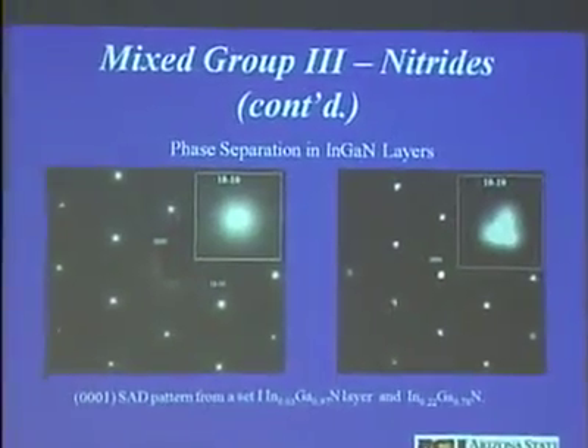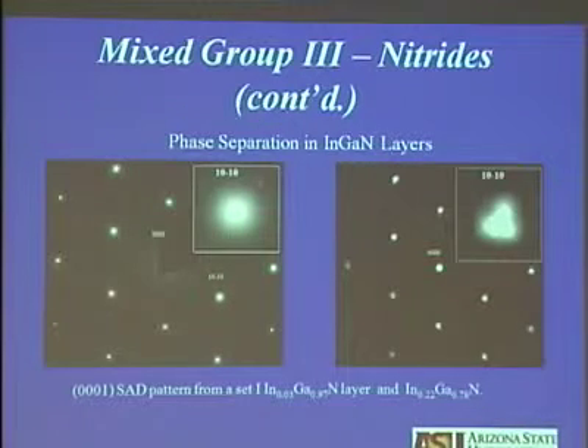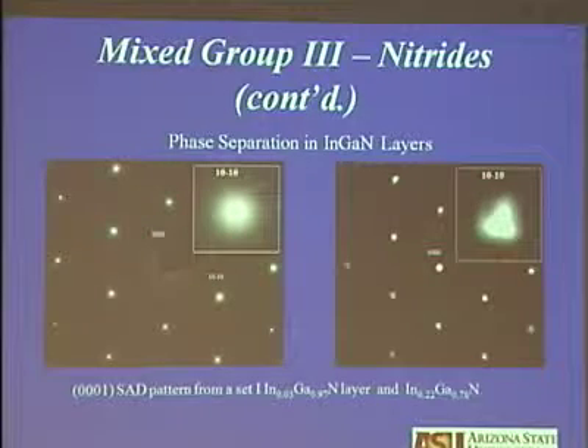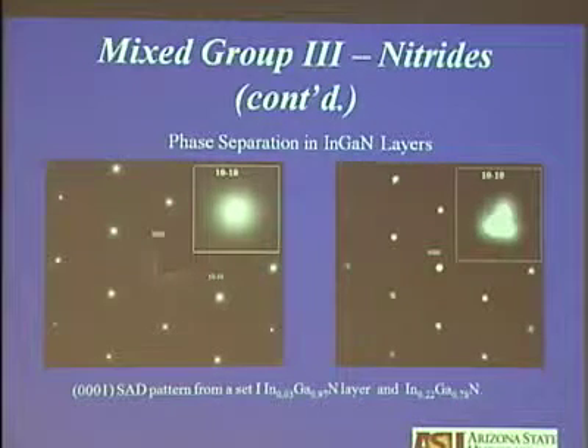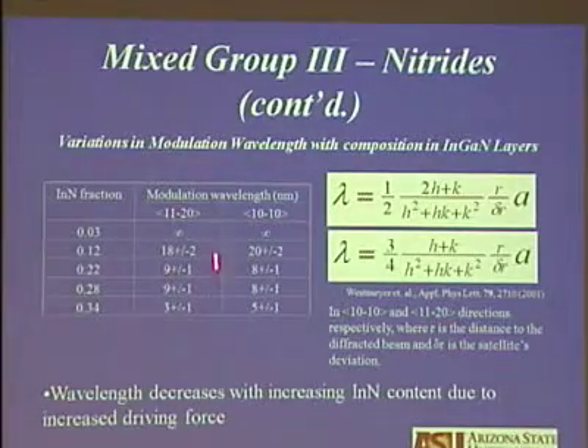These blue DVD lasers or LEDs that you see are based on indium gallium nitride. And you can change the composition of indium, and it will change the emission wavelength. When you are below a certain value, look at 3% of indium, the diffraction spots are spherical. You go to 12%, 22 in this case, and spots are no longer spherical and they have satellites. And as I said earlier, from the position of the satellites, you can determine the wavelength of the modulation in these materials. We have done these studies over a range of compositions.